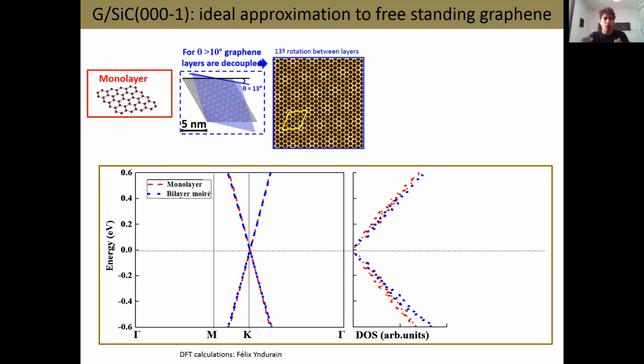So now we are all aware of the works on magic angle graphene. In magic angle graphene, it means you have two layers which are rotated just 1 degree. And then you have a lot of electron-electron coupling between both layers. And due to this electron coupling, you have the appearance of very interesting phases such as superconductivity and magnetism. But here we go to the opposite limit. Instead of rotating 1 degree, we rotate the graphene layers a lot. So once you rotate the graphene layers more than 10 degrees, the graphene layers become electrically isolated from one another. Of course, I'm talking about low energies.